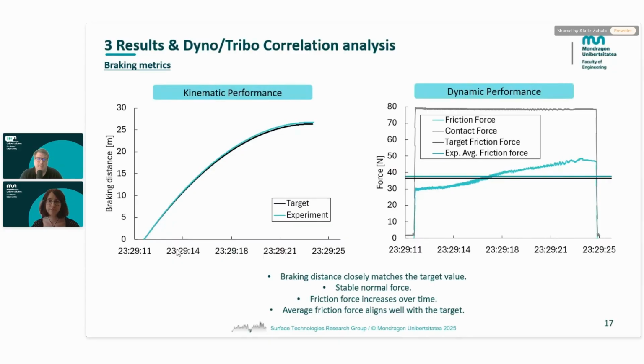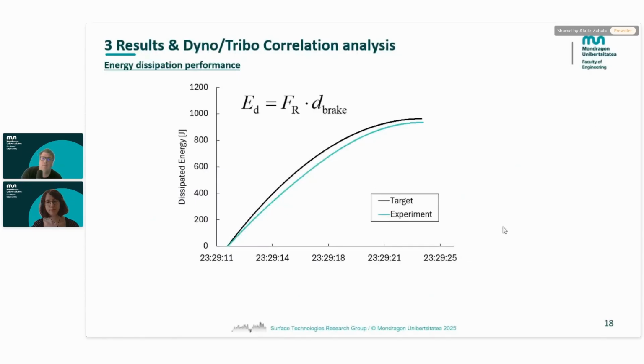Regarding the dynamic performance on the right-hand side, again, on the x-axis we have the time, and on the y-axis we have the force. Checking the contact force, we can see in gray that we have quite a stable normal force. And in contrast, with the friction force we can see that we have an increase over time. And this is because we have fixed the normal force, and the friction force is the evolution of what happens during the braking. So again, we can compute the average friction force, and we can see that the obtained average friction force is quite close to the target that we have. So once we have defined these values, then in the next slide, we can compute the dissipated energy, and we can see the results.